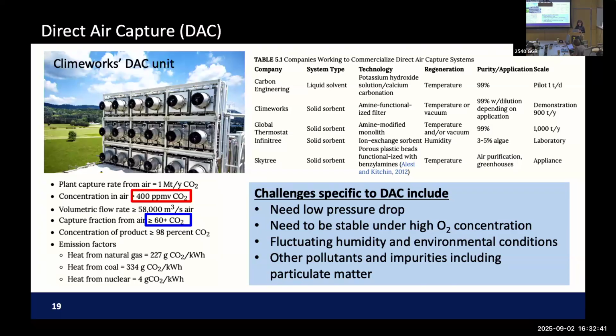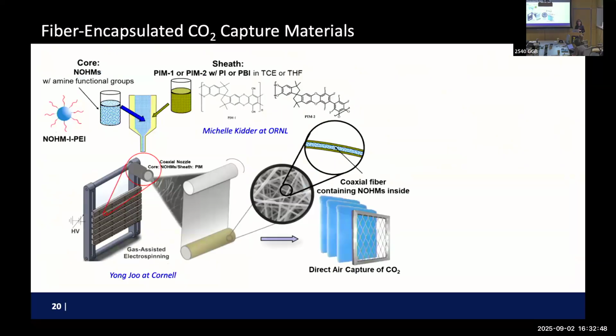So I started thinking that instead of making that encapsulated particle, I wanted to have a low pressure drop. So we started thinking, how about electrospun fibers? My friend at Cornell, Young-Ju, did a lot of electrospinning of fibers for fuel cell applications. So I said, okay, Young-Ju, can you make this with my NOHMs material staying inside, not outside, because it would be very sticky, and it also collects a lot of water. But my friend Michelle Kidder at Oak Ridge National Lab, whom Andrea knows very well, was making this PIM material, which is a polymer with really, really good porosity. I wanted the PIM to be outside and the NOHMs inside, to make an electrospun fiber that looks like this, so that we can control the overall pressure drop to be very low. And we were actually able to do it.